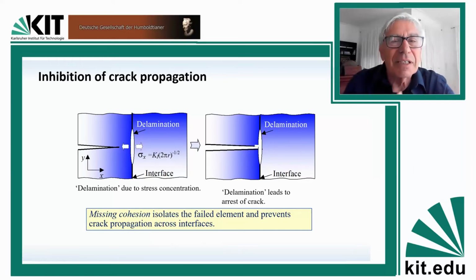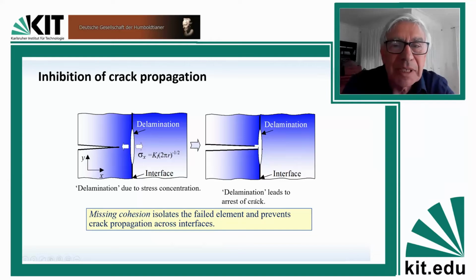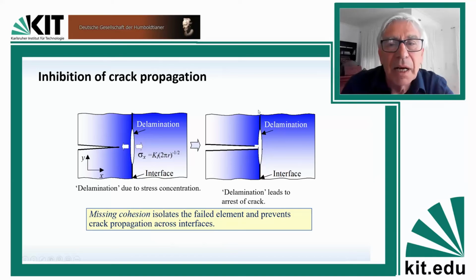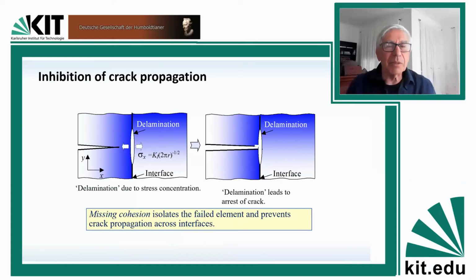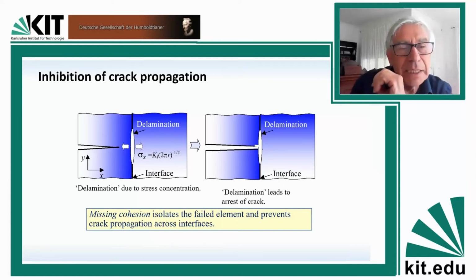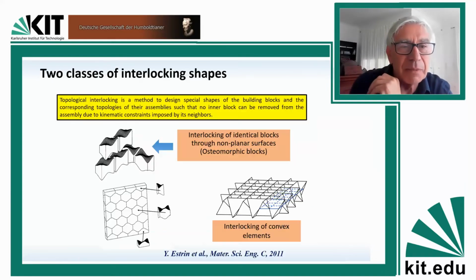If you have a structure assembled from elements and have interfaces here, a crack propagating from one element and hitting the interface just produces delamination here, but the crack will be blunted here, and it will propagate in some other way, but a much more complicated way, along a much more involved path, and that means a higher energy dissipation. So you would get an increased resistance to crack propagation, to failure.